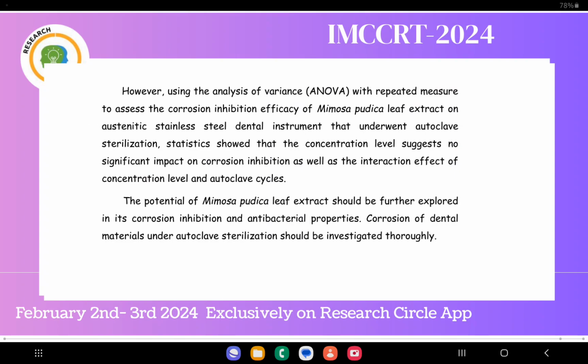However, using the analysis of variance, or ANOVA, with repeated measure to assess the corrosion inhibition efficacy of Mimosa pudica leaf extract on austenitic stainless steel dental instrument that underwent autoclave sterilization, statistics showed that the concentration level suggests no significant impact on corrosion inhibition, as well as the interaction effect of concentration level and autoclave cycles. The potential of Mimosa pudica leaf extract should be further explored in its corrosion inhibition and antibacterial properties. Corrosion of dental materials under autoclave sterilization should be investigated thoroughly.